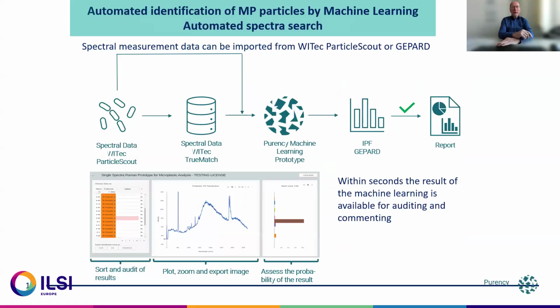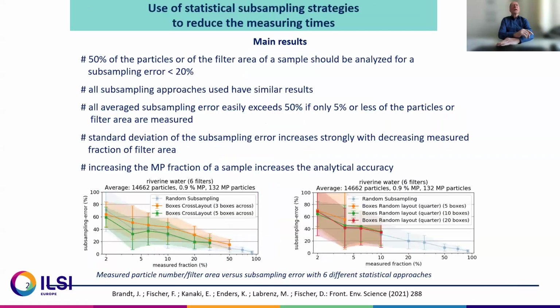If you use a machine learning approach, it's very easy. You can also use the spectral data and put this data directly into the machine learning tool, and within seconds you have the result. This is available for auditing and commenting. The advantage is that you can use the raw spectra from the measurement, as shown here, for example, and you can see that this is polyethylene.